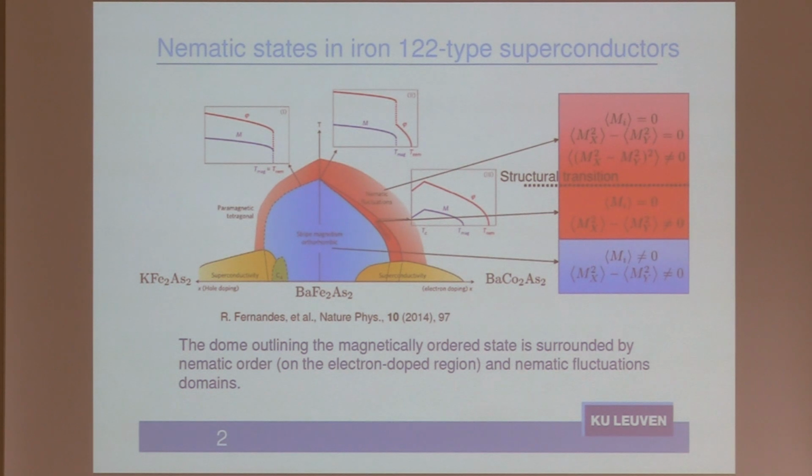And this can be a pure spin type, called the spin-driven Ising nematic state. When we calculate the average of mx squared and my squared, the square of the magnetization in x and y, this corresponds basically to measuring the susceptibility xx and susceptibility yy. They start to differ, and this is the order parameter of this spin-driven nematic state.